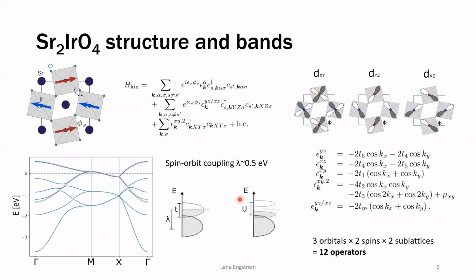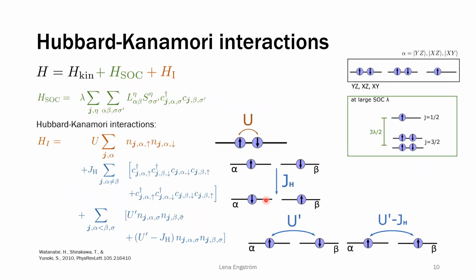However, if we add interactions, we can see that this picture becomes more complicated. So we want 3 orbitals, as before, 2 spins and 2 sublattices. So we will be using a 12 operator basis. And now that we have several orbitals, what we need to consider with the interactions is that we no longer just have this Hubbard U, but that we actually have interactions both that is this U, that is within the same orbital, where we do have repulsive interactions, but we also have interactions between orbitals. Here, the J_H is the so-called Hund's coupling, which is fluctuation between different orbitals, and which tends to destroy some intra-orbital orders. And we also have this repulsive U prime that also is between orbitals.